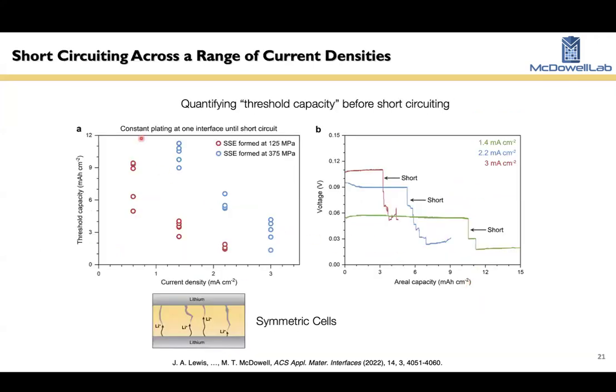So that's a problem. This is just a map that's kind of showing that these short circuits are pervasive, and they always form in these sorts of ceramic electrolytes with relatively low density. And we think this is related to growth through some of the pores in the solid electrolyte, or at least exacerbates the fracture process. But this just kind of illustrates that these dendrites and filaments are quite difficult to prevent unless you can have careful processing of these materials.